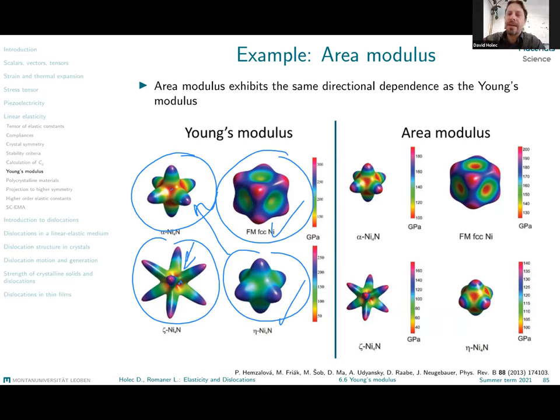The Young's modulus in one of those directions is extremely small. And small Young's modulus means that a deformation in such a direction does not cost you any energy. That means your material can be elongated without inputting any energy, without doing any work. And this is a sign of elastic or mechanical instability. When you look here, the spatial distribution of area moduli is the same as for the Young's moduli.